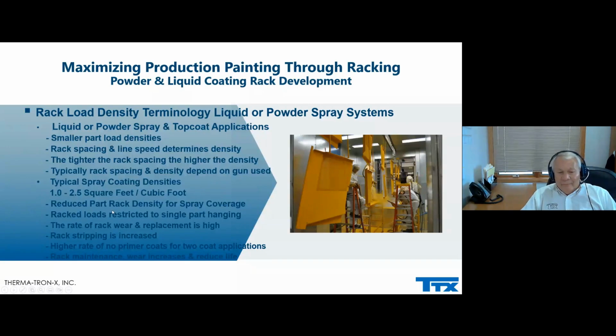Again, for spray coverage, it's important that the densities can be kept up through rack spacing. You can maximize the amount of parts on a rack just by having basically a complete sheet wall, even if it's small parts. If you have a full sheet of sheet metal that you're applying the coating to, it's the most efficient. You can control the film build much more closely. But when you have small parts spaced widely, it's very difficult because you get a lot of wrap and you're trying to compensate for any Faraday cage effects.